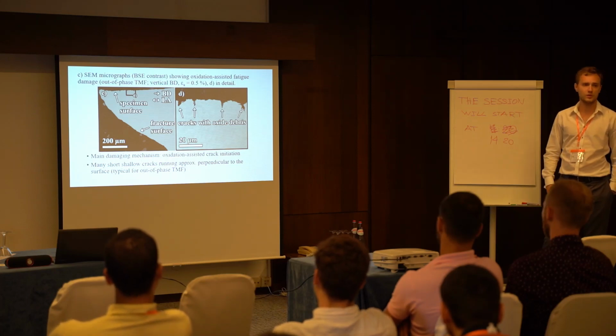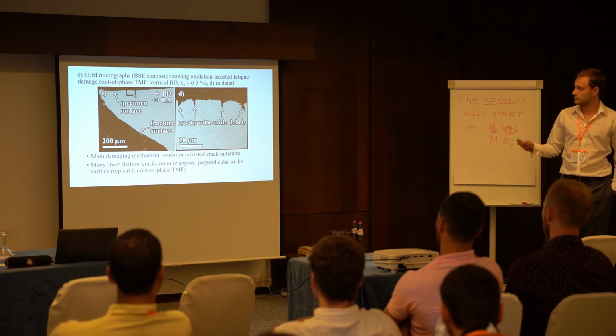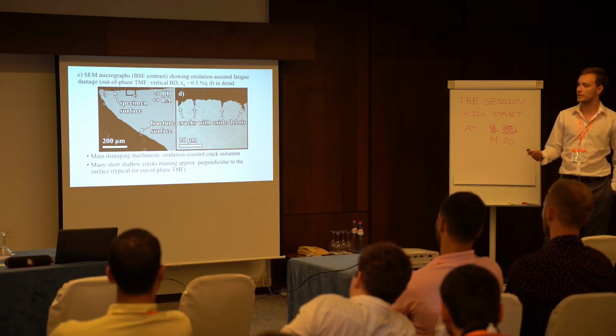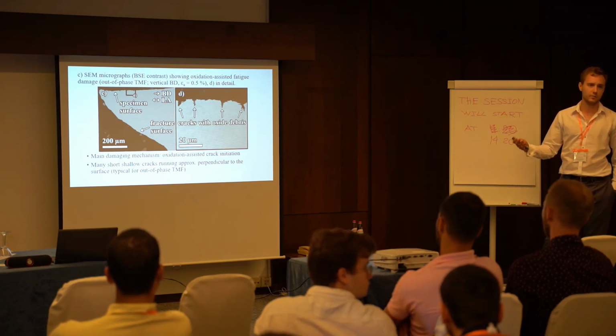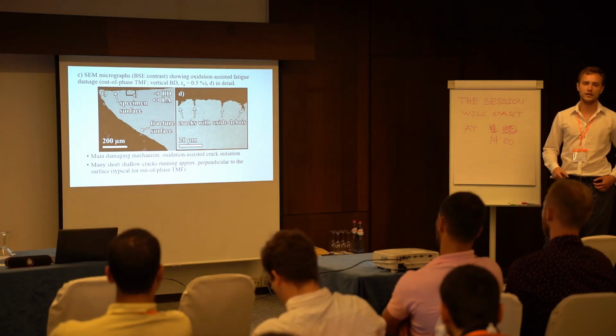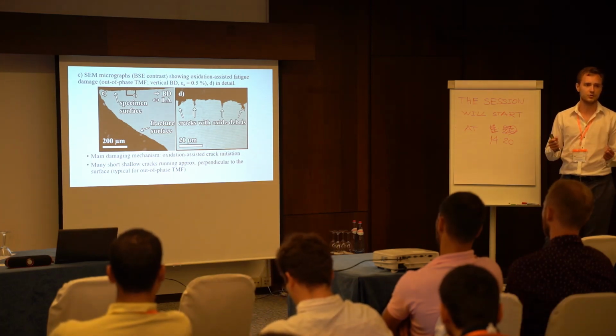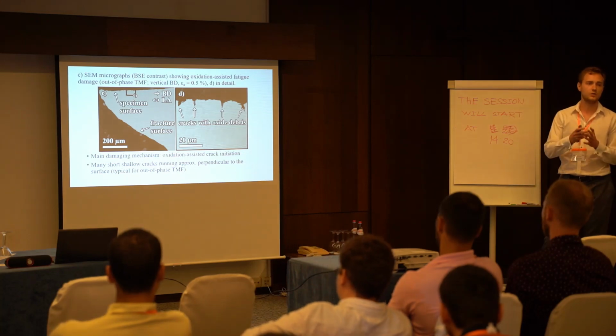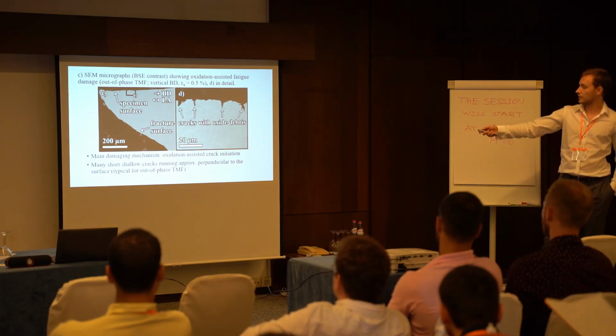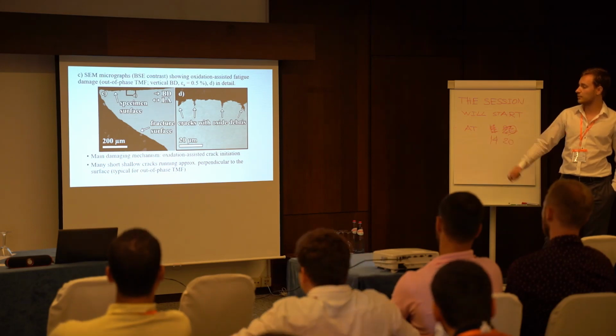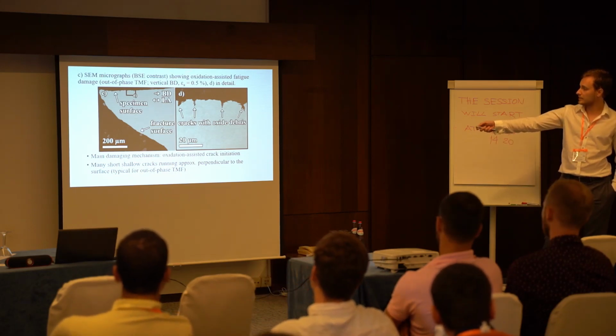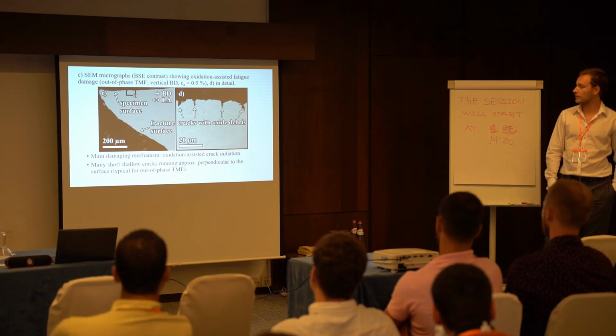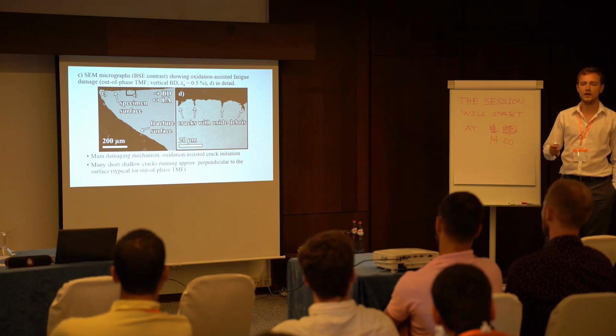And this picture also shows us the acting mechanism. So it was oxidation-assisted crack initiation. The oxides which were formed on the surface at higher temperatures were easily cracked at lower temperatures with the tensile stress field, which is the reason why we had so many cracks at the surface. This feature is actually also typical for out-of-phase tests in general. There were many cracks, running approximately perpendicular to the surface, and they were short and shallow. So the lifetime was generally governed by propagation of the principal crack, not those small ones.